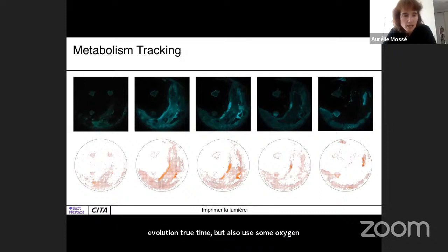oxygen sensing based on the dynamic quenching of an oxygen sensitive indicator dye by oxygen to actually validate our hypothesis that oxygen would deplete gradually from the medium through time and through the growth of the colony, which we made obvious by working with the University of Copenhagen on that specific point.